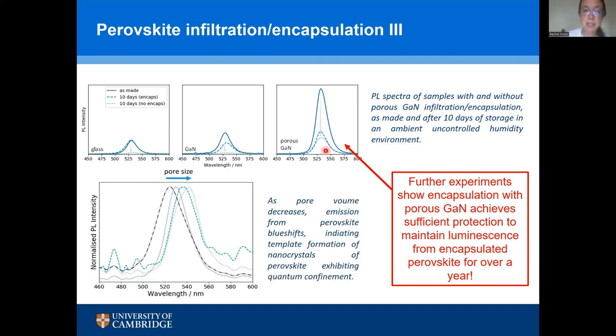We could also see that by putting the perovskite into different size pores in gallium nitride, we could see different wavelengths of the luminescence. And that's because we're templating the formation of different size nanocrystals using the pores.